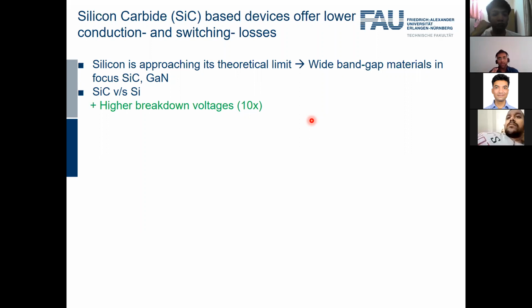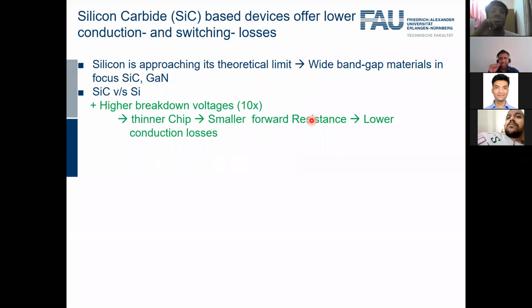So this means silicon carbide has a 10 times higher breakdown voltage compared to silicon. And this means with the same thickness of device, we can achieve a 10 times higher breakdown voltage of the device compared to silicon. Or for the same breakdown voltage, silicon carbide can be 10 times thinner compared to silicon. So this means there is a huge potential to bring down the forward resistance, which is dependent on the thickness of the drift layer. And this means we can reach lower conduction losses.